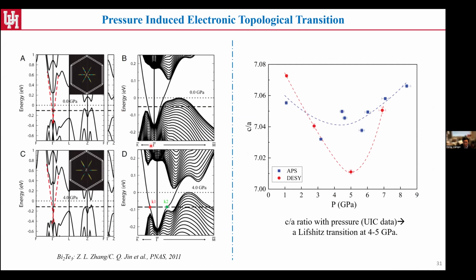So go back to the nice X-ray results. When we plot C over A against pressure, we can see a clear minimum around 4 to 5 GPa, right? That indicates the possible Lifshitz transition does happen at this critical pressure, and that matches pretty well with the critical pressure that changes this material from non-superconducting to superconducting while still keeping the same crystal structure, okay?